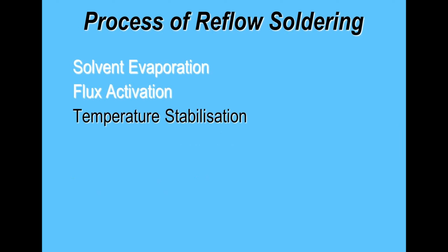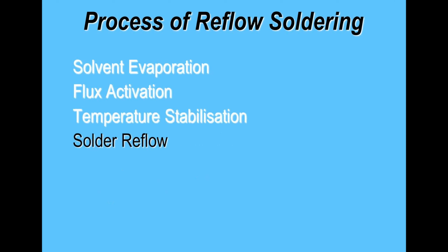Temperature stabilization, this is basically the dwell, making sure that all of the terminations and areas of the PCB to reflow are at a consistent temperature. Now, this is important to make sure we can minimize peak temperatures and also optimize the process. This is a lot easier in a nitrogen environment than it is in an air environment, but we must make sure that we've got sufficient time to get all terminations up to a consistent temperature prior to moving into reflow. Otherwise, you'll get inconsistency. Solder reflow, the paste becomes a liquid, and it forms a solder joint, provided everything before has gone to plan.